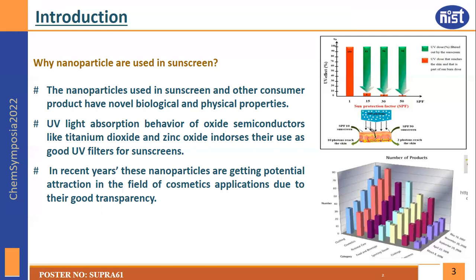The UV light absorption behavior of oxide semiconductors like titanium dioxide and zinc oxide endorses their use as a good UV filter for sunscreen. In recent years, these nanoparticles are getting attention in the field of cosmetic applications due to good transparency in the nano domain. Titanium dioxide as well as zinc oxide are well-known UV absorbers in the bulk as well as in the nano form. But in the nano range, it retains its UV absorption efficiency in spite of being a very transparent material. This is one of the most attractive, promising applications of this nanoparticle in the field of sunscreen.